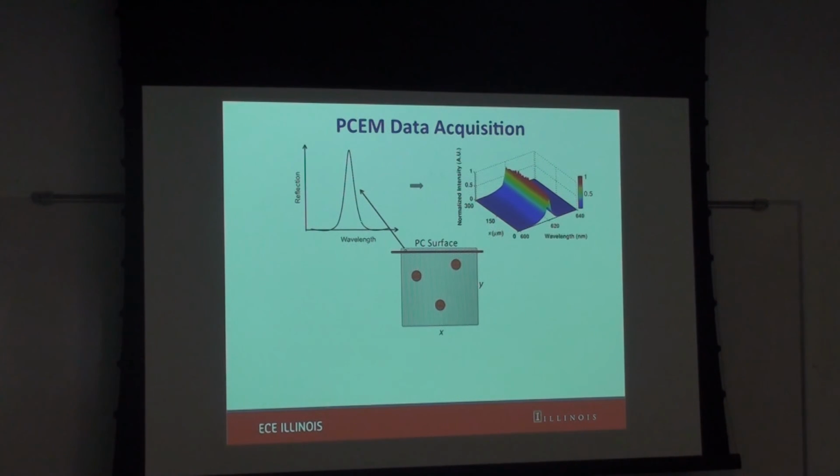Have you tried higher index materials to get better Q factors, or for the titanium oxide, is that the highest that you can? Yeah, having a better quality factor will give more enhancement. It doesn't necessarily make the amount of shifting more. We can manipulate the quality factor a little bit by choosing the refractive index of the material, or the thickness of the grating or depth of the grating, things like that. We have a trade-off.